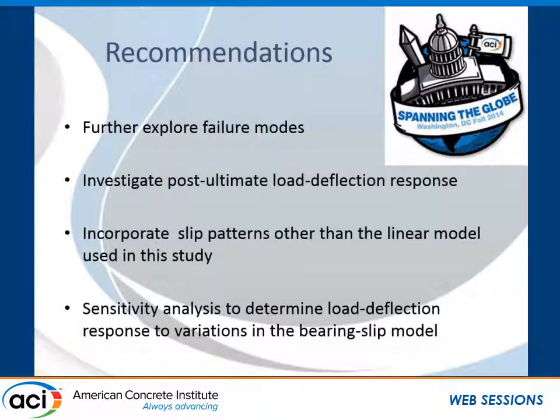To a certain extent, it would depend upon the particular failure mode. If failure is going to be by FRP rupture, what would probably be recommended is 0.55. If failure is going to be by yield of steel followed by concrete crushing, 0.9.